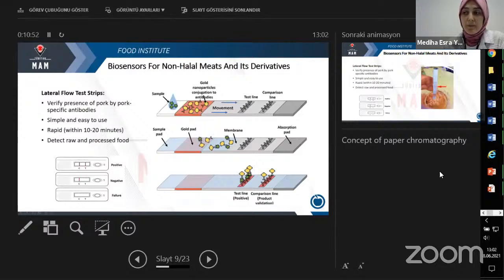You know, it's very easy to use. You just put the sample on it and wait for the result. If there are 2 lines, that means it's positive. If there's 1 line, that means it's negative. And if you don't see any line, that means it's a failure, so you have to repeat the test with another test strip. So how does it work? You can see the V-shaped antibodies here attached to the gold nanoparticles.